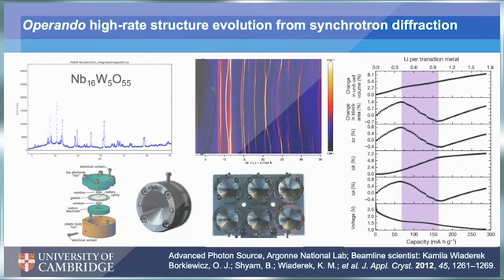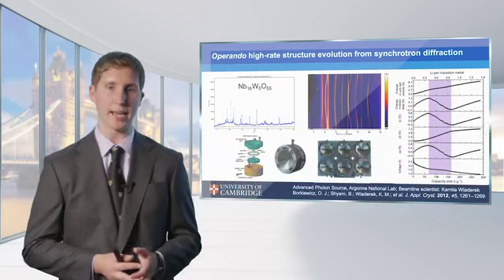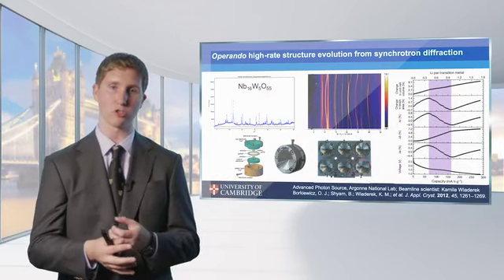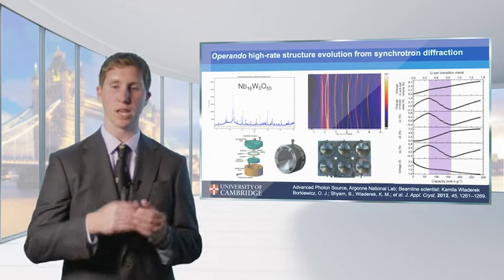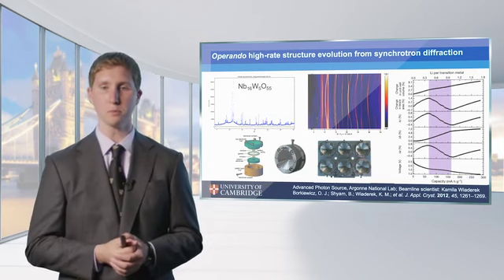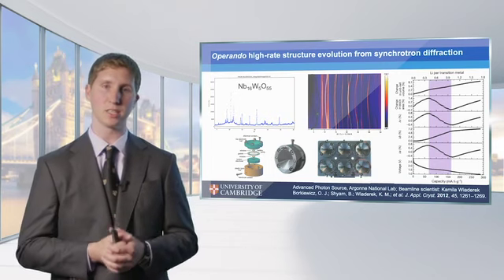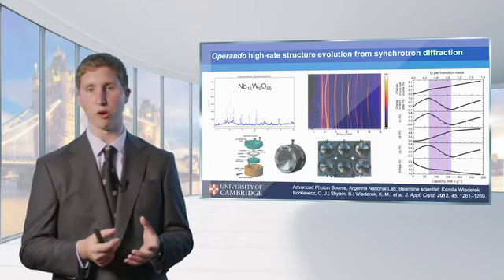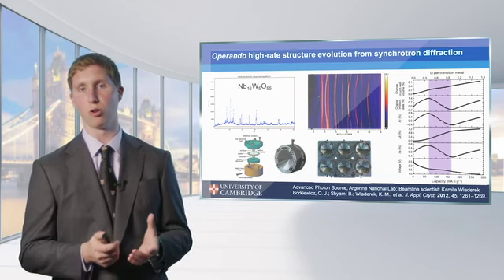And so what we see in the crystallographic shear structure, and is seen in other crystallographic shear structures as well, is that there's a three-phase evolution. So initially the blocks of our Wadsley-Roth phase start expanding, and then in the middle stage they contract. And they actually contract to smaller than where they started, which is relatively unique, that as we're adding atoms to the system, as we're lithiating, part of our structure is contracting in response to this. And then the layers of those are monotonically expanding. But because of this anisotropy between how our lattice is evolving, we have an overall small volume expansion.